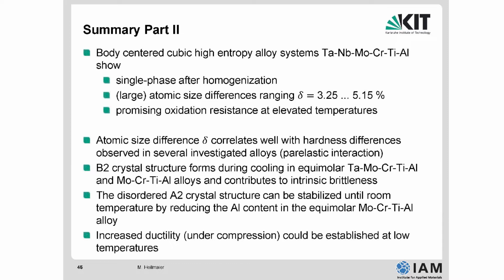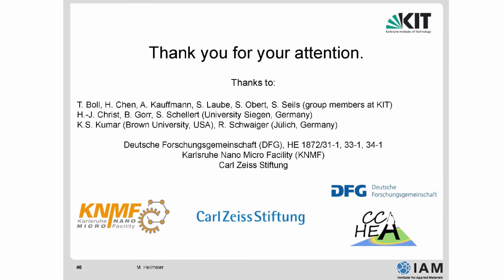The disordered A2 structure, simple BCC, can be stabilized until room temperature by reducing the aluminum content, and this then gives rise to an increased ductility at these low temperatures. And with that, I'm at the end of my talk.